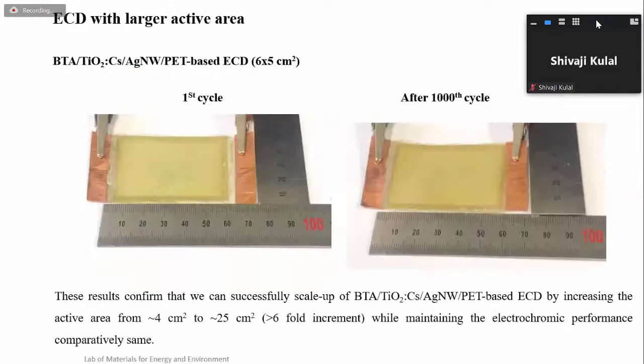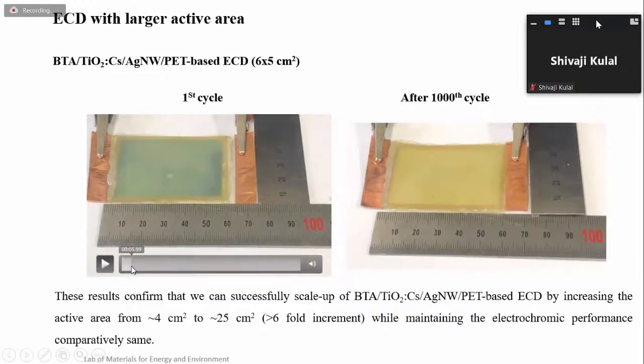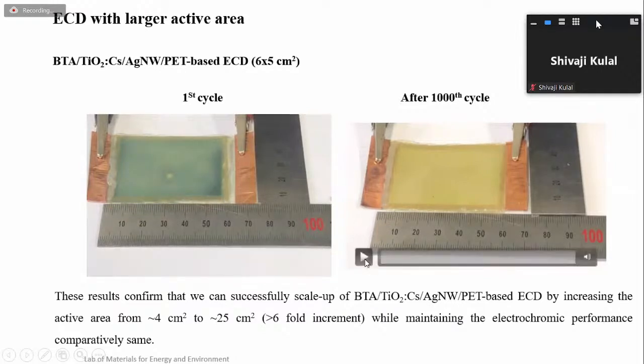So this is one of the devices I made, a big device with a 6-fold increment. For the first cycle, we can see that the device is changing its color. And I tested after 1000 cycles, it's also still working. So these are initial experiments to show the capabilities of the silver nanowire based electrode for flexible electrochromic devices.